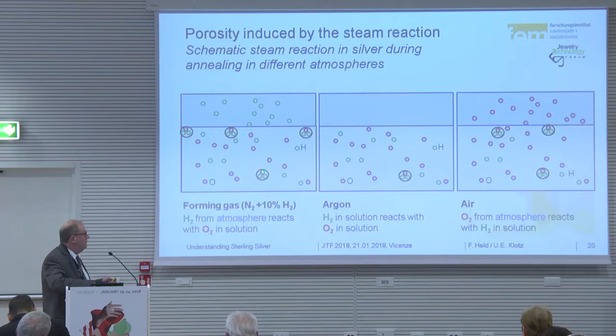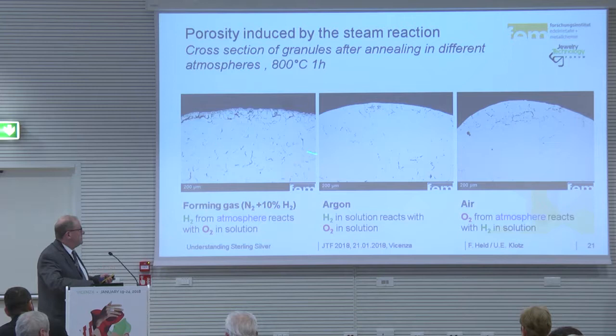You have it in all three atmospheres, but in forming gas, you have the most, so we know that there is much more hydrogen in the granule than oxygen. This is a metallographic cross-section of the granules, and you see here, in forming gas, you have the most porosity from water steaming. Argon, you also have the porosity, and in air, and this looks not very fine. That's not what we want to use.